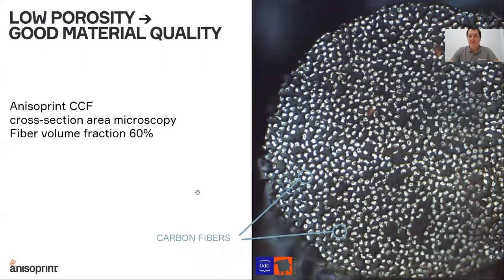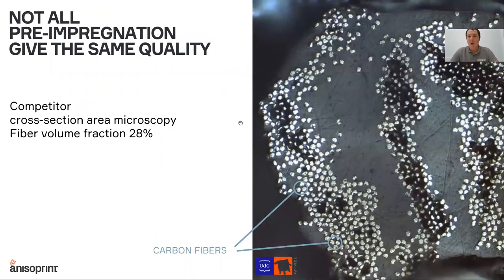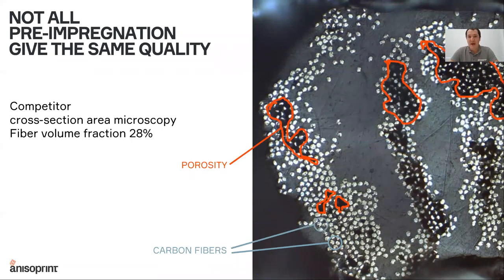What can similar material, similar fiber look like if the impregnation is not so good? This is an example of how it can look with improper impregnation. So you can see a lot of black spots inside the cross-section area. You can also see the white dots, the fibers. You can see the black areas, which are highlighted.